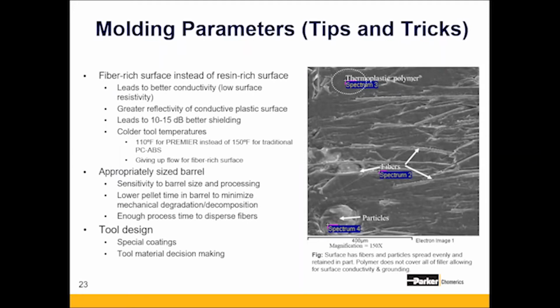Another area you want to make sure you have covered, and you understand, to get your best performance, is you want to take a little time to make sure that the injection unit on your molding machine is properly sized. Ideally, you want about 3 to 4 shots in the injection unit. So say you have a 4-ounce injection unit on your molding machine, and the shot size of your part or parts is 1 ounce. That's ideal. Then you know that by the time the molten plastic gets to the nozzle and gets injected into your mold, it's properly processed.